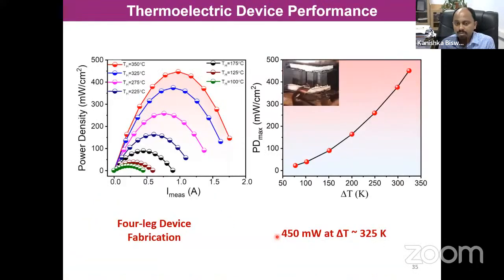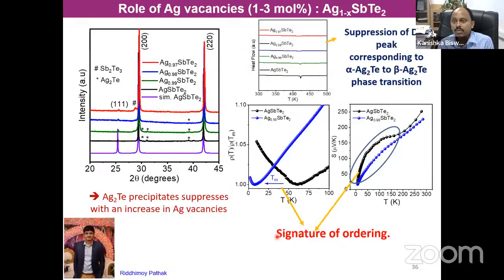So then what we have done, we have created a 4-leg device, which gives very high power, with an efficiency of around 6 to 7%, which matches market-based material. So then we went ahead and created silver vacancy in this compound, because silver creates lots of disorder in this compound. So we wanted to remove some of the disordered silver so that we can have atomic ordering. So actually it creates much better atomic ordering than cadmium doping. And this work has been done by my PhD student Riddhimay.